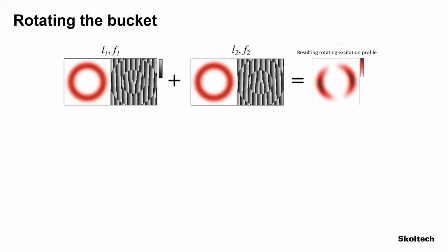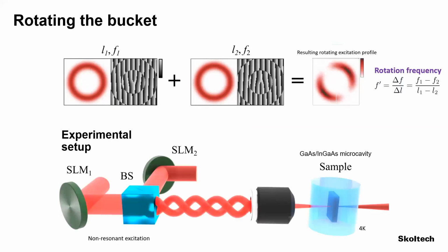So when we do that, we use two spatial modulators, two lasers, we mix them, we pump the structure, we pump the exciton reservoir like that. And when I look now at the polariton condensate emission, the dotted ring is where we pump. The color that you see here is the intensity of the light that comes from the condensate. It forms a very nice vortex, really a very clear circle of the polariton condensate, in the center of this bucket where I pump the carriers non-resonantly. And if I look at the energy dispersion here, I have a clear single mode state.